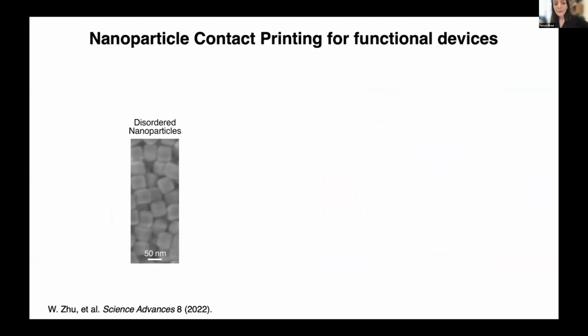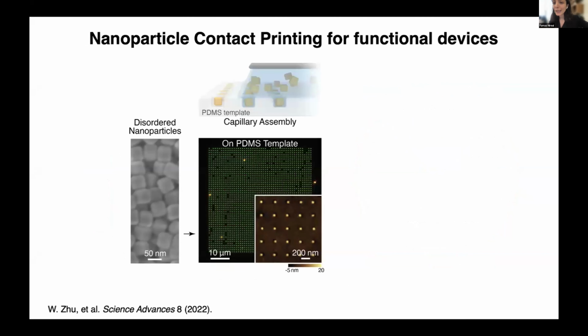So in one approach, what we've developed is nanoparticle contact printing. I'm describing the approach to you here using gold nanocubes as an example material. So in this approach, first we use capillary assembly to assemble the nanoparticles onto a topographical template that is lithographically defined. I'm showing you here an array of 50 by 50 nanocubes.